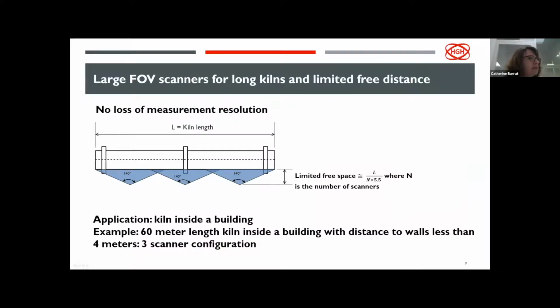Another challenging case is when the free distance between the line scanner and the kiln shell is limited. In that case, we use our 140-degree field of view option so that the distance between the scanner and the kiln shell can be very short. As an example, for a 60-meter length kiln inside a building with a distance to walls less than 4 meters, we can integrate three scanners side by side, each of the scanners aiming at 1/3 of the kiln shell.